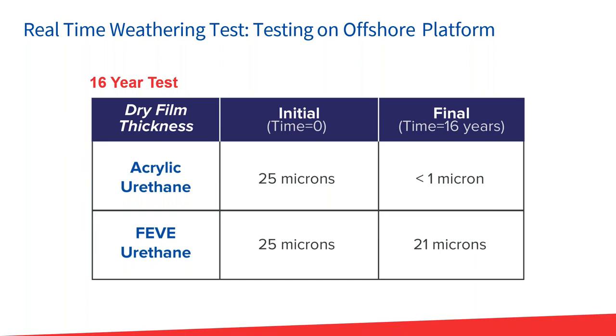So they measured film build at the start, roughly 1 mil. And then after 16 years of exposure, the acrylic urethane was essentially eroded away. So you can imagine if that happens, there's no corrosion protection going on at that point. Whereas with the FEVE urethane, you have 21 of those 25 microns, so you still have very good corrosion protection.